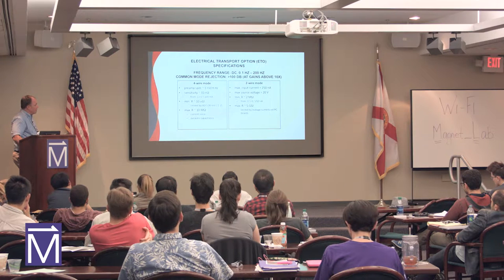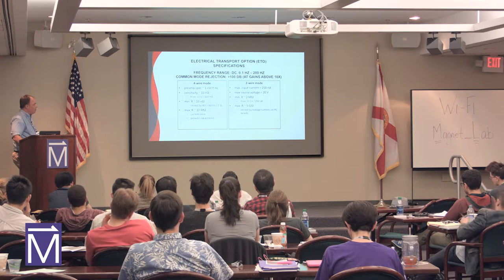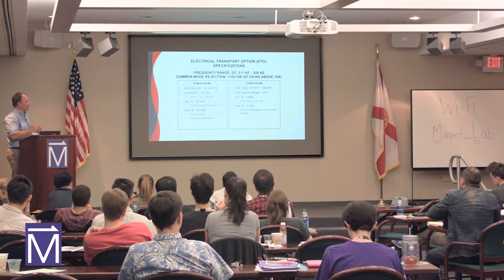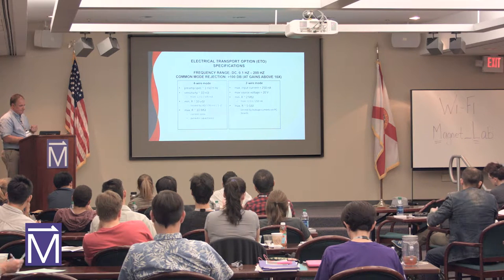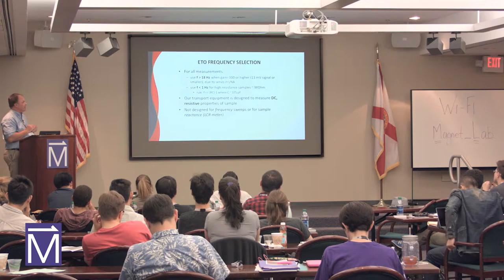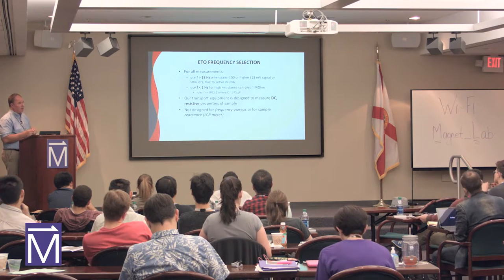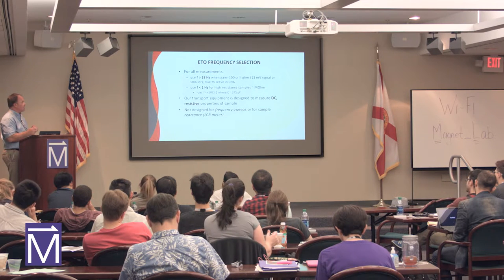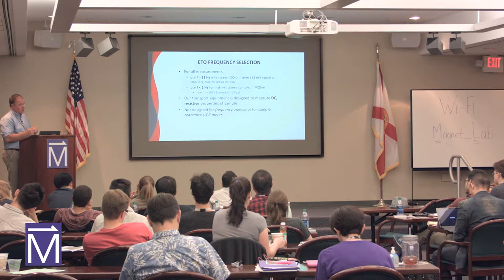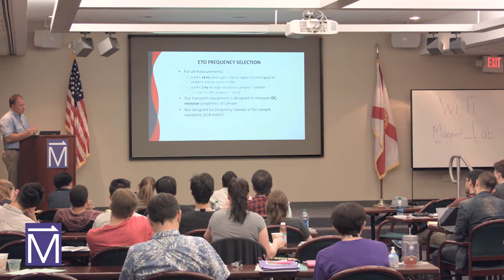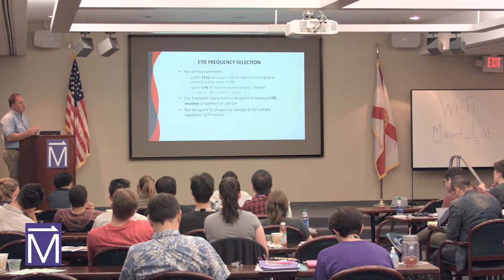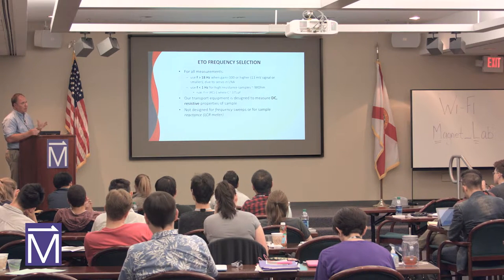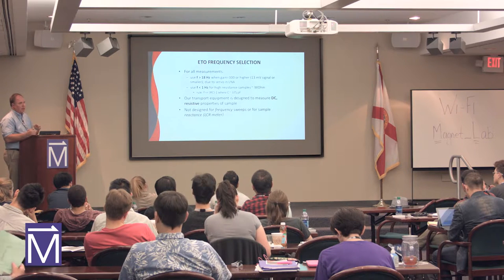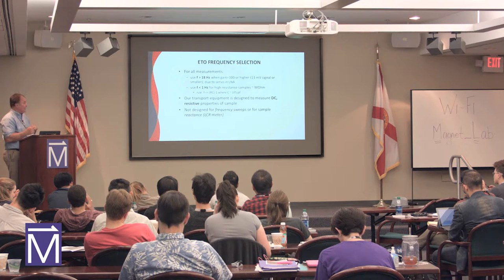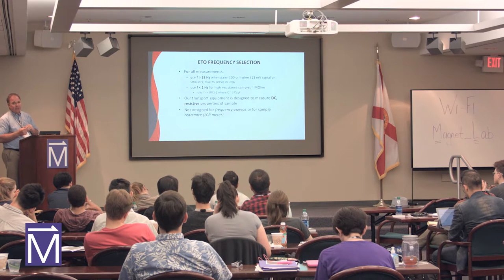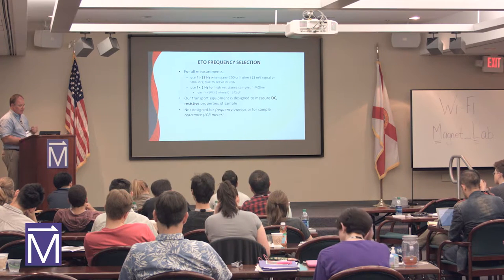What's the key thing here? Maximum resistance on the four wire, 10 megaohm, and then 5 gigaohm on the two wire type measurement. Selecting the frequency: obviously you want to select frequencies for the measurement that are away from 60 hertz, 50 hertz type measurements. So we recommend using greater than 18 hertz when you have a gain setting of 300 or higher, less than a hertz for high resistance samples, and the system's designed to measure DC resistive properties. So it isn't an LCR bridge or LCR meter impedance analyzer. You're measuring DC resistances with these things.